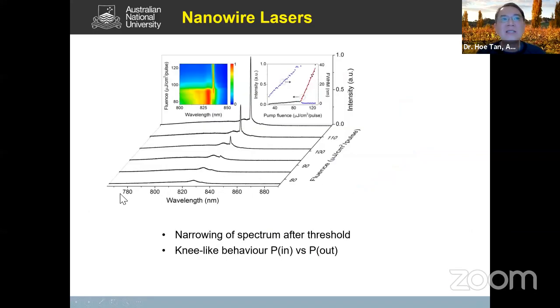So plotted here is the spectral data from the nanowire as a function of excitation power. Okay, you can see here, at very low excitation power, there is just a very broad emission, just like LED action. As you increase the excitation power, one of the modes starts to dominate, and this mode becomes stronger and stronger as you increase the excitation higher and higher.